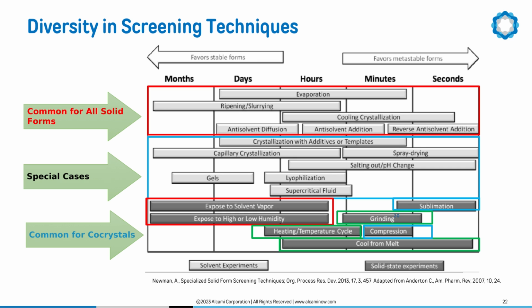Slower or longer term conditions, which are shown on the left side, favor thermodynamically stable forms, whereas faster conditions, shown on the right, favor metastable forms. Early screens usually involve common screening techniques, whereas comprehensive screens, which are done later, use a combination of most of the listed techniques. A typical amount of solid needed per one crystallization experiment requires a few tens of milligrams. However, some very specialized automated platforms can operate at 1 milligram scale or lower.